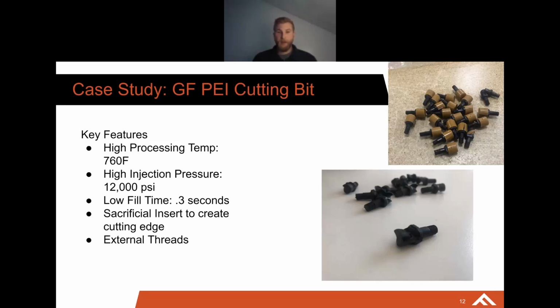That took our design time from a day, maybe 2 days, down to a few hours. Less than a few hours, actually. It's probably an hour and a half. It takes about 10 minutes to design that insert, and then maybe an hour to put in all the ejector locations and a few other things. But those threads worked with the mating piece perfectly, and we ended up getting a really nice part out of glass-filled ULTEM.